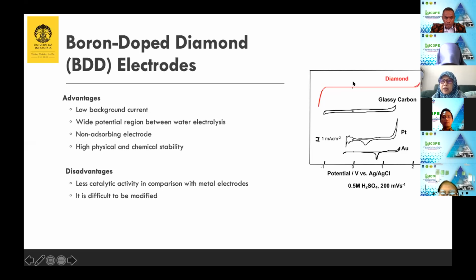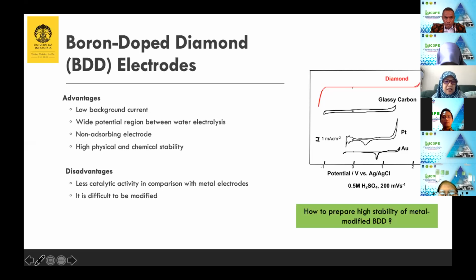So diamond has a wider potential in comparison with other electrodes, and it also has a lower background current. Why do we need low background current for sensors? Because generally low background current can provide very small noise, and then we can get a better limit of detection. So we can see here diamond in comparison to other electrodes has low background current and a wider potential region between water electrolysis. Diamond also, because it is an sp3 material,